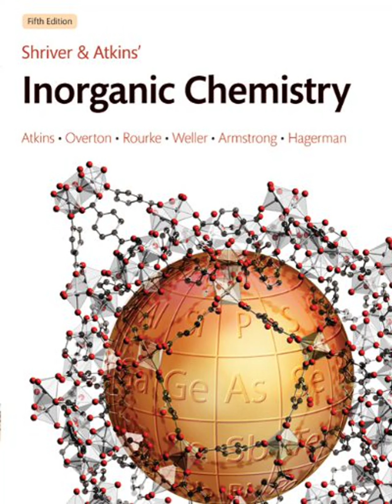Exactly. It shows why you need very high temperatures in a blast furnace to reduce iron oxides with carbon or CO, and even higher temperatures to reduce silicon dioxide. But some metals are too reactive for this. Yes, highly electropositive metals like aluminum or sodium, their oxide lines are very low on the Ellingham diagram. For them, you need electrochemical extraction, electrolysis, using electrical energy to force the non-spontaneous reduction, like the Hall-Héroult process for aluminum. Fascinating application of thermodynamics.